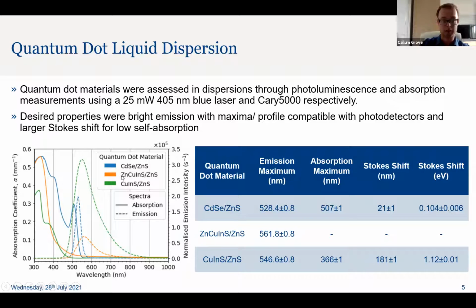And so the idea was initially that the zinc would increase the band gap and end up with a bluer emission. However, that hasn't been achieved, and it ended up reducing the brightness. I should say that we haven't manufactured these quantum dots on site. These are all commercially available. So at the moment, they're relatively expensive to buy, but if we could start synthesizing them on site for projects outside or after my PhD, the cost of them is going to dramatically decrease.